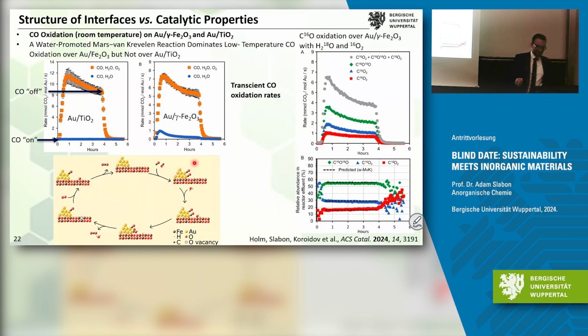It takes part in the reaction because you have the gold and the iron oxide. You have the adsorption of CO. When the water kicks in, it gets adsorbed and splits into OH and H. Then you have spillover over the interface, you generate the CO2, and you're left with a vacancy behind, which is a preferential adsorption site for oxygen.